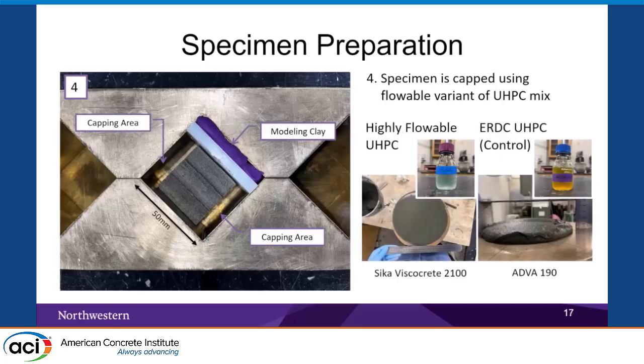In the base mix, we used ADVA 190. To make it really flowable, we used Sika Viscocrete 2100, and it makes it really flowable. You can see here in the flow table, it's really flowable so that it can fill any gaps, so that we can have a good capping and eventually a good barrel and smooth surfaces for loading conditions.